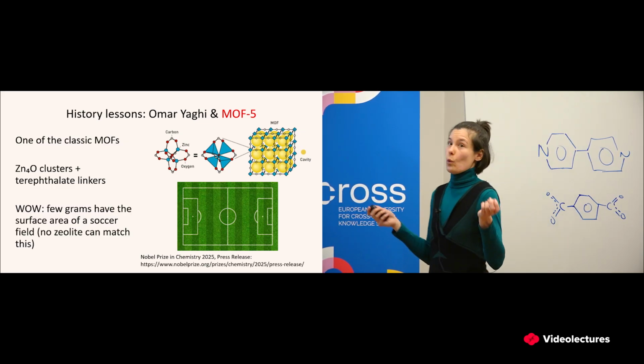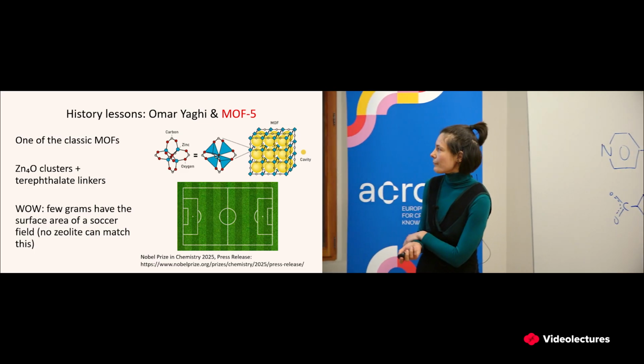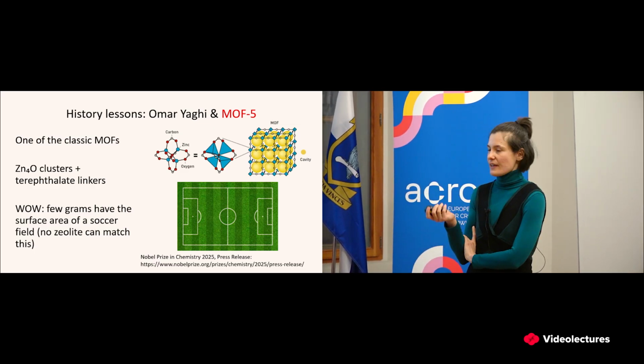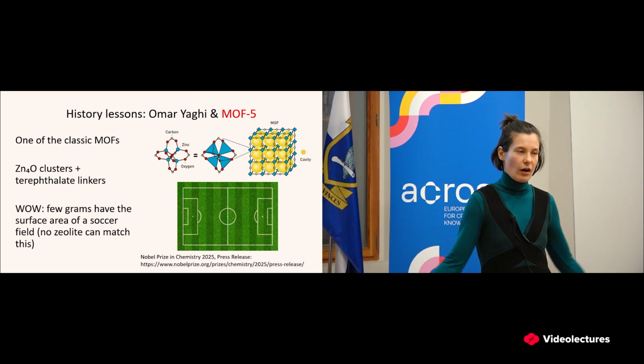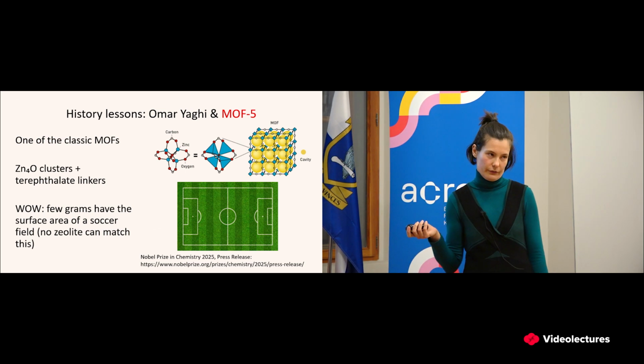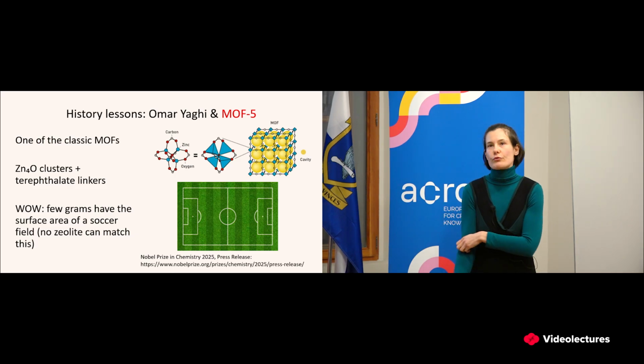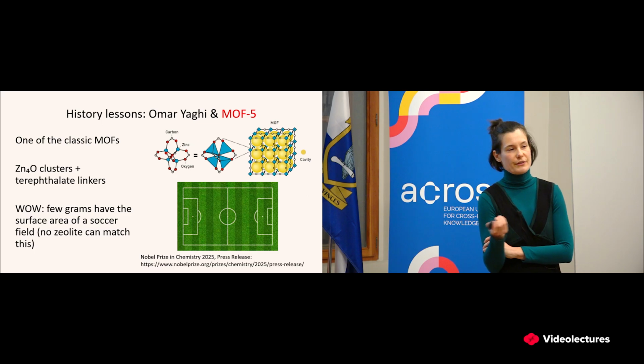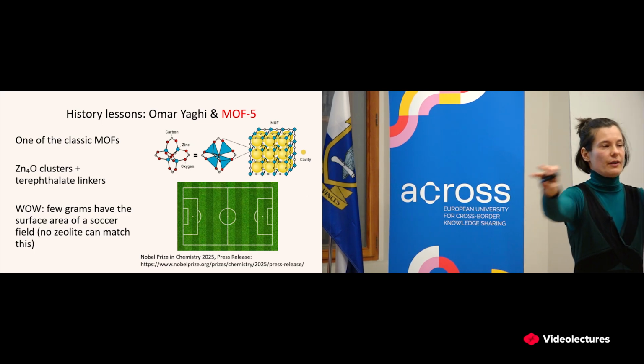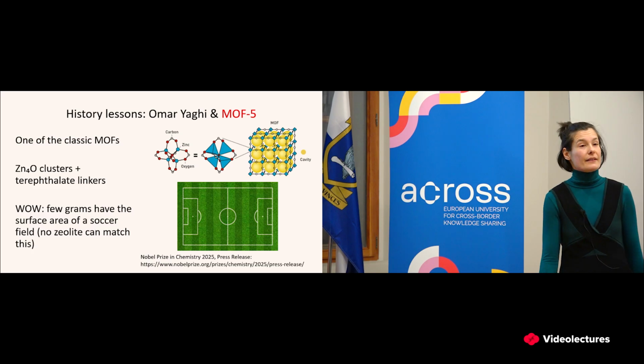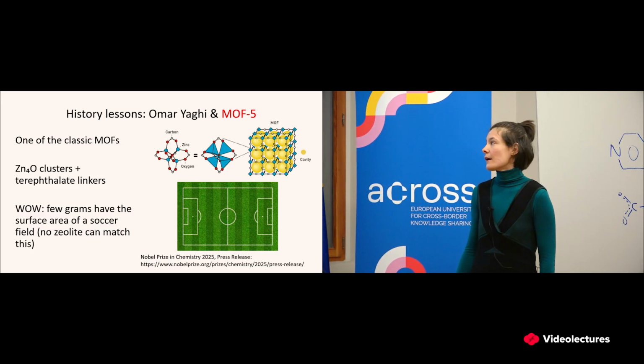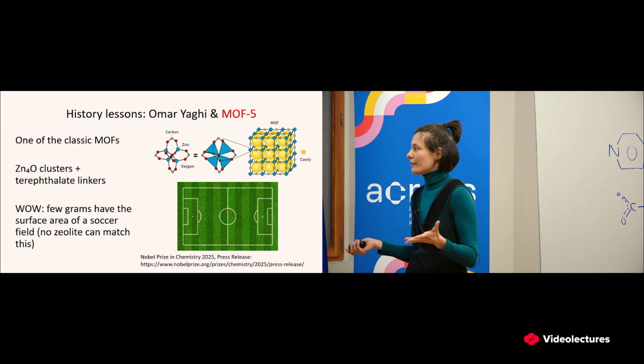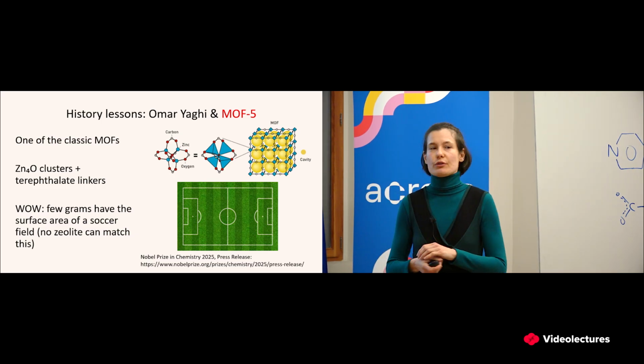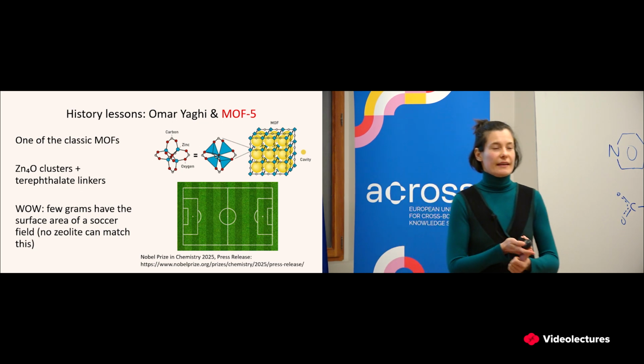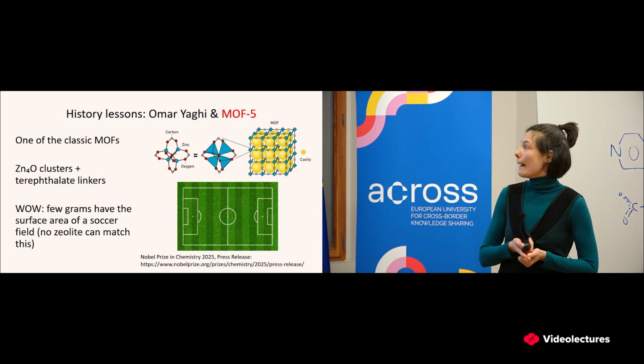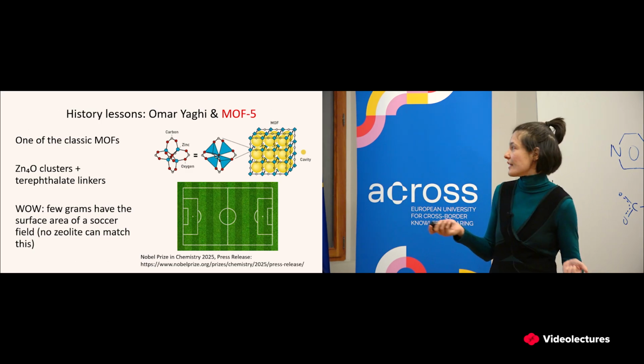So why was this MOF so wow? The reason was its very large surface area. If you have a gram of this substance, the total surface area of this material would be the size of a soccer field, right? Nowadays there are MOFs with surface areas as high as 7,000 square meters per gram. So 1 gram would have a surface area of 7,000 square meters. And this value is much higher than what zeolites can achieve. So this was yet another point where MOFs could be proven superior to zeolites. They can have higher surface areas than zeolites, and they can also exhibit this soft nature.